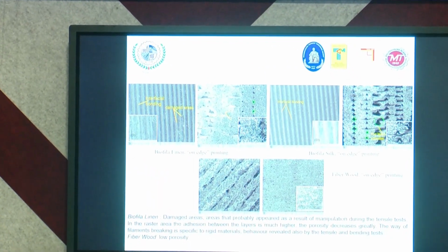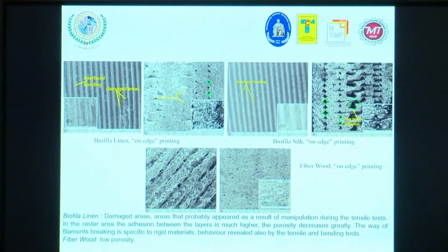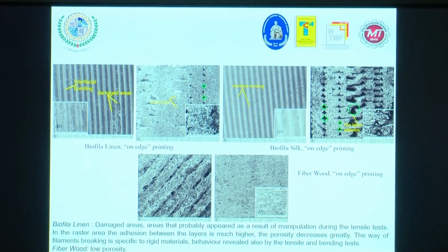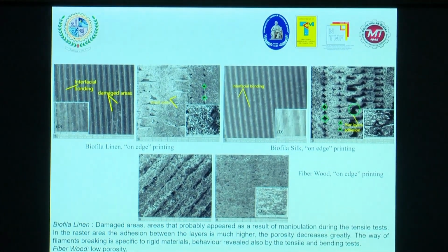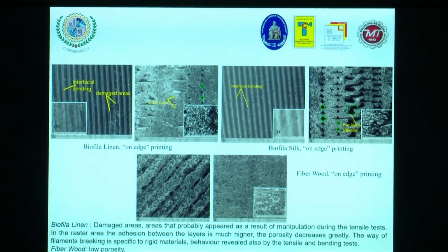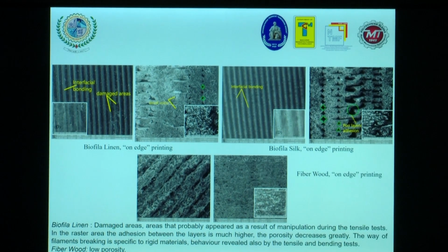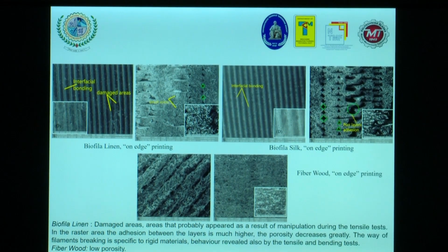Also, I would like to carry on together for biodegradable material. Biofila linen on edge, Biofila silk also, you can see SEM images on edge, and fiber wood also on edge printing. In case of Biofila linen, you can see some damage area that appears probably as a result of manipulation during the tensile test, because we didn't find another reason why a little bit of damage area appears.